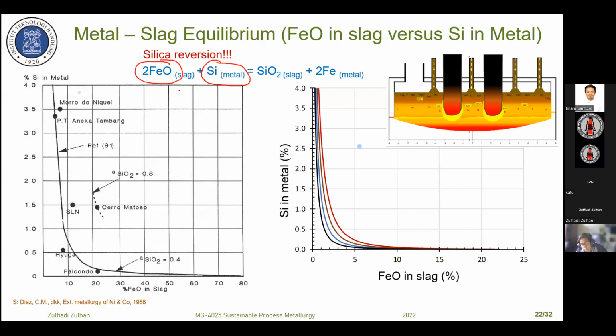in the metal. In general, if we want to have a high silicon content in the metal, we should reduce the iron oxide content in the slag. This is a diagram also from Professor Diaz, in 1988. There's a correlation between iron oxide in the slag and the silicon in the metal. If you want to produce ferronickel with high silicon content, we should reduce the iron oxide.